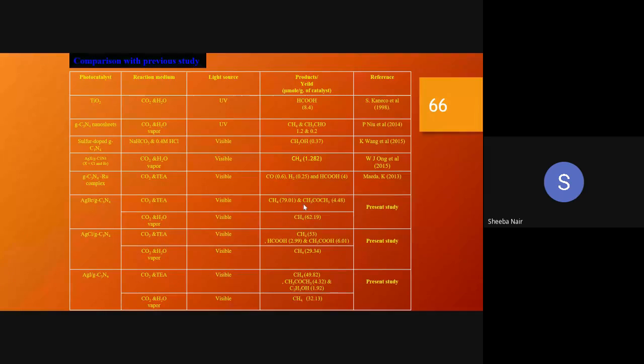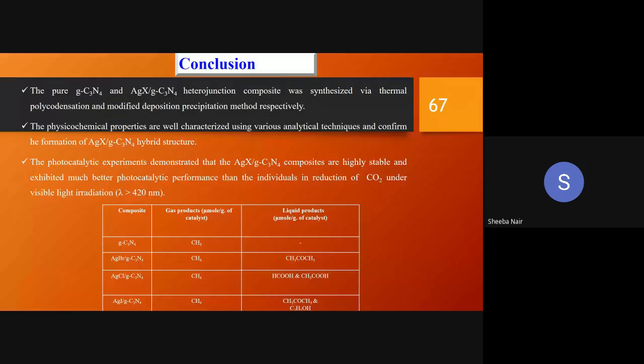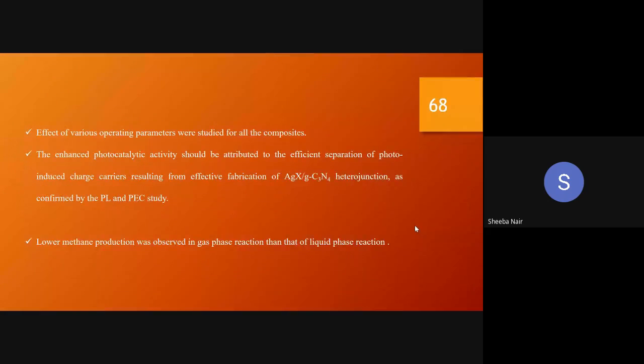So methane and acetone. You can see the nature of products: methane, acetone, ethanol, HCOOH, etc. Methane was more in number. Methane was the major product out of the system in your gas phase study also. So all the photocatalytic experiments and the stability experiments conducted in the lab showed that they are very highly stable and they can perform better in the CO2 conversion than the normal semiconductor materials.